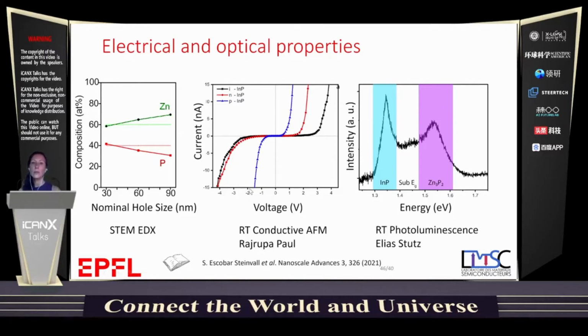Here in the middle, we looked at the electrical properties by growing the zinc phosphide on P-type, N-type, and intrinsic substrates. We see that the intrinsic substrate shows Schottky behavior. The P-type also shows Schottky behavior with lower resistance, while on the N-type we have a diode-like behavior, showing that the zinc phosphide is P-type, as we would expect from the previous studies, and opening the way to creating p-n junctions and solar cells.